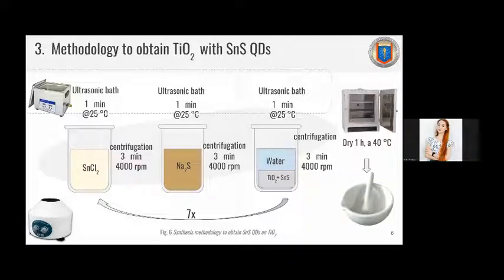Afterwards, the collected titanium dioxide was added to sodium sulfide, which is the second step. The same process was done: an ultrasonic bath for 1 to 2 minutes, then centrifugation to remove the liquid part, the water part. As a third step, it was washed with distilled water to prevent ions from the previous unreacted material from reacting with the next step of tin chloride, because it can react and form unwanted salts that we wanted to avoid. The whole process was repeated for 7 cycles and then dried at 40 degrees Celsius for 1 hour. And then the characterization was done on the powder.